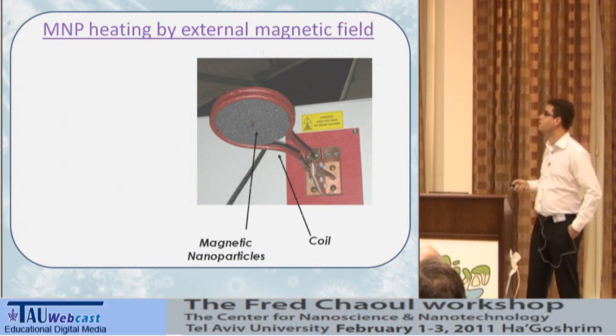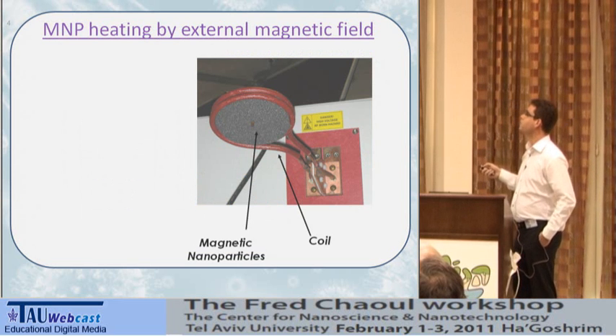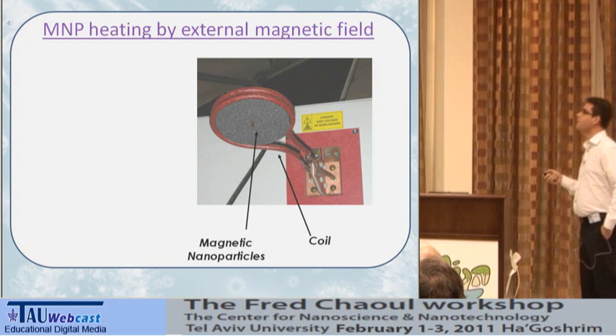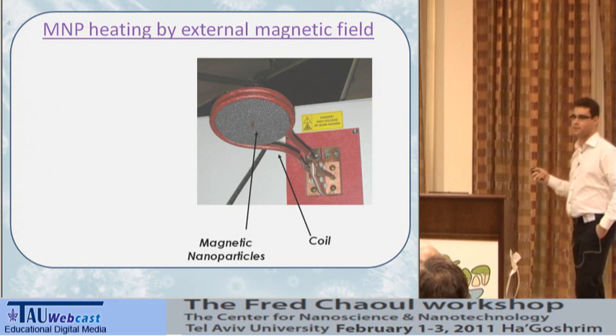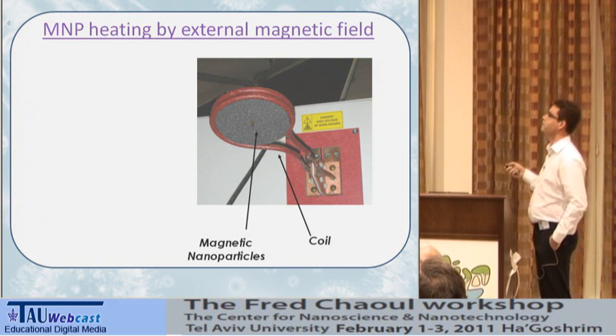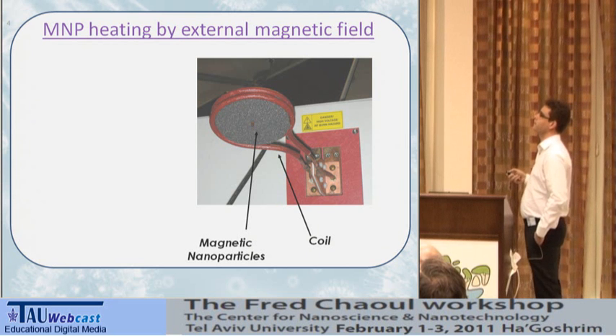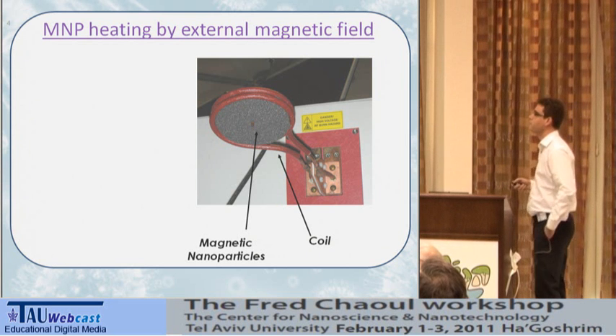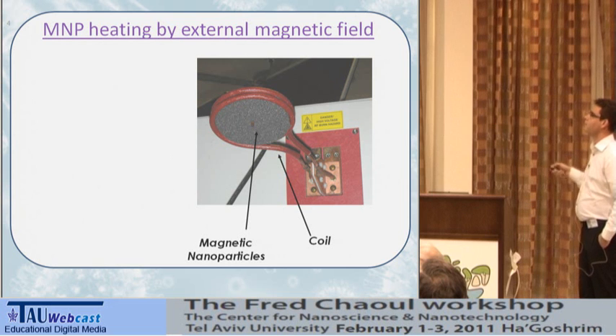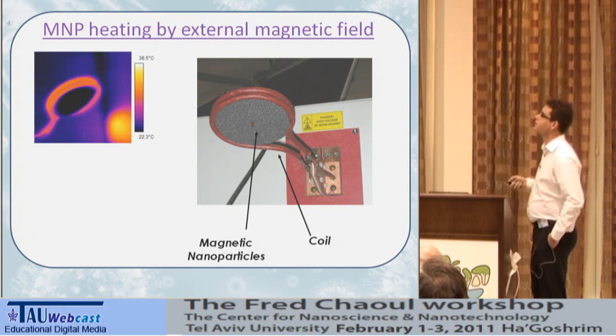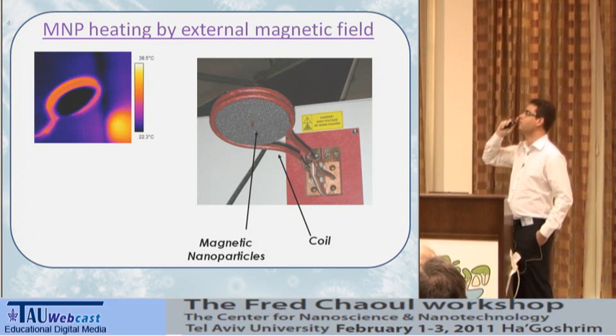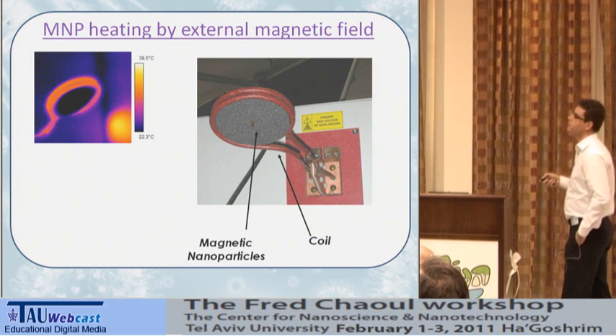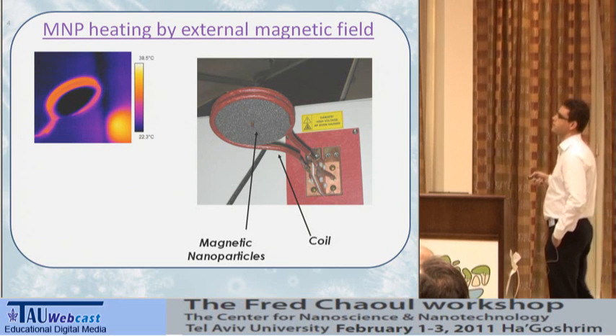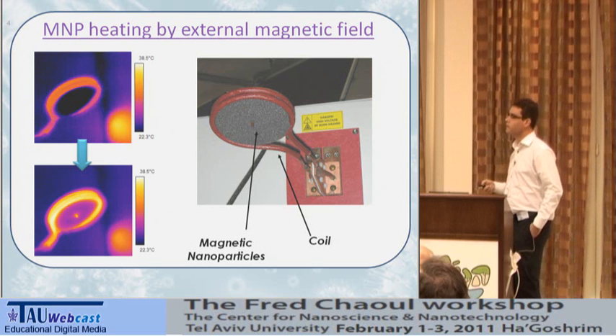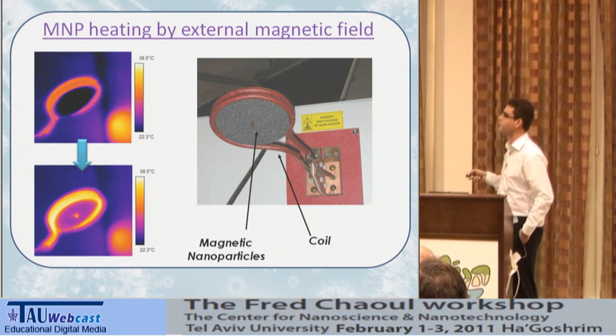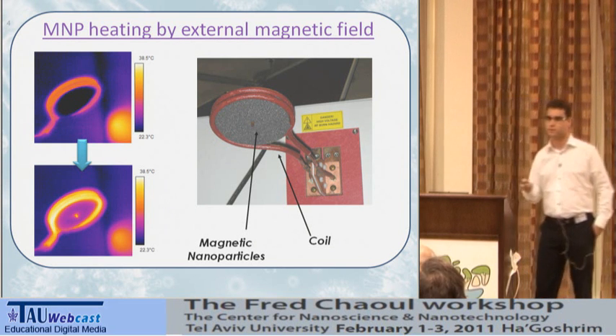And as you can see here, we took a machine for welding pipes, an industrial machine that has a coil and generates a magnetic field. We put a vial of magnetic nanoparticles at the center of the field, and we took pictures with the thermal camera. In the beginning, you see only the coil that heats up because of the current. And after a few seconds, you see the nanoparticles also heat due to the magnetic field.